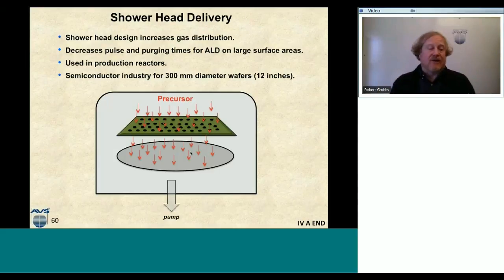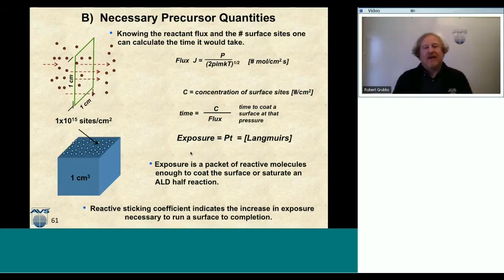So that ends the section on just precursors and the delivery. But now let's talk about the actual necessary quantities that we need to perform ALD chemistry. So we talked about flux here in the cartoon, and we talked about the number of surface sites per centimeter squared. Now I have an equation for flux right here. I have a concentration of surface sites, which is 10 to the 15 per centimeter squared. So if I divide the concentration of surface sites by the flux, I'll get the amount of time that it takes to coat that particular surface at that pressure.